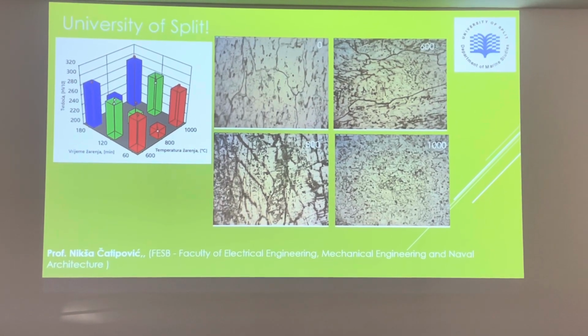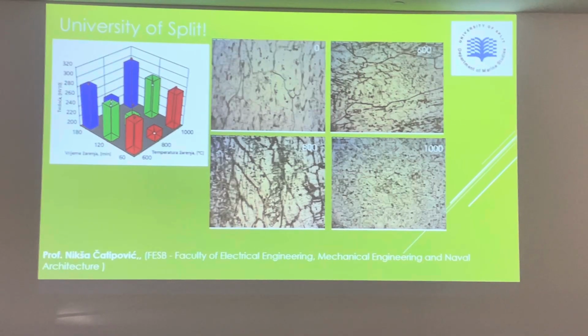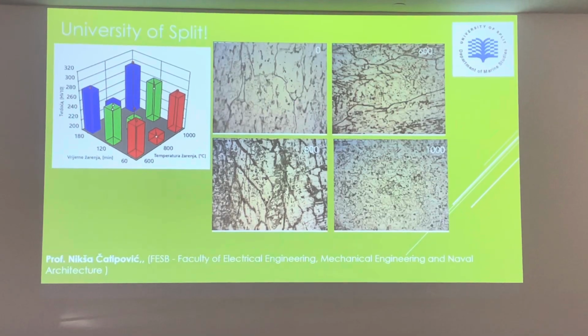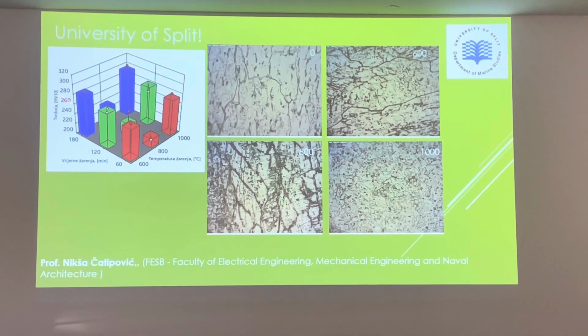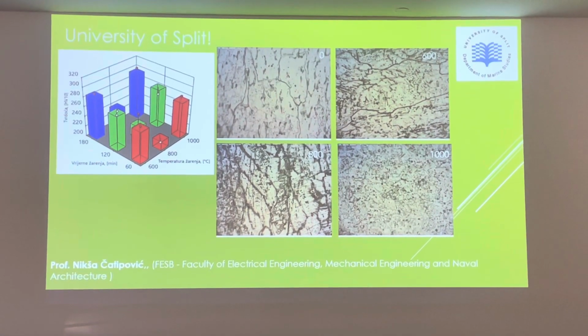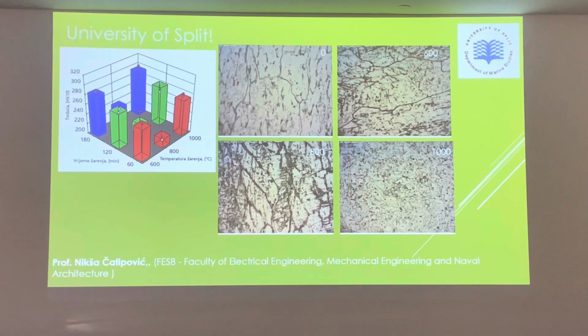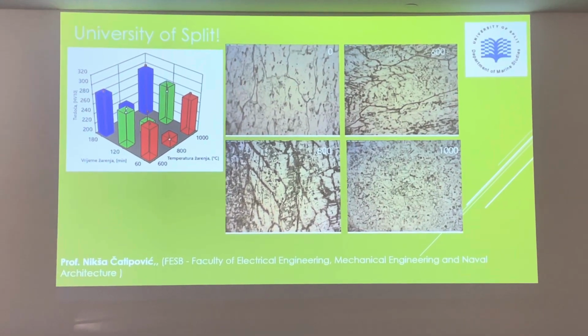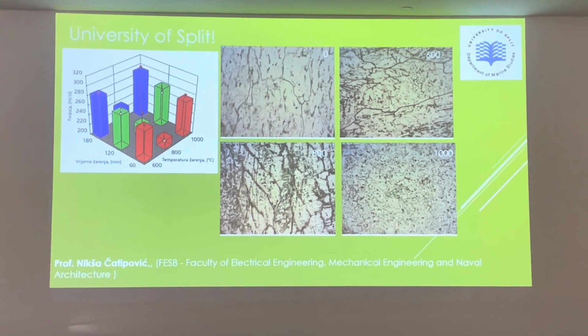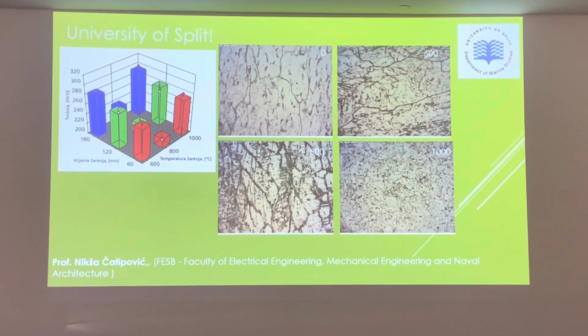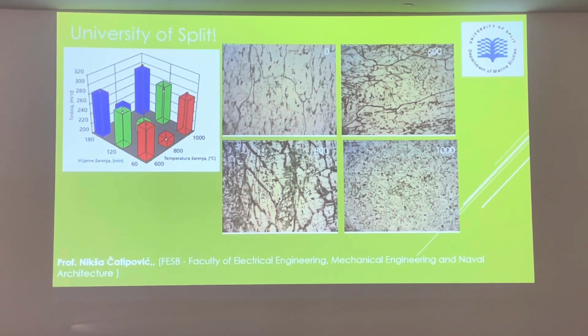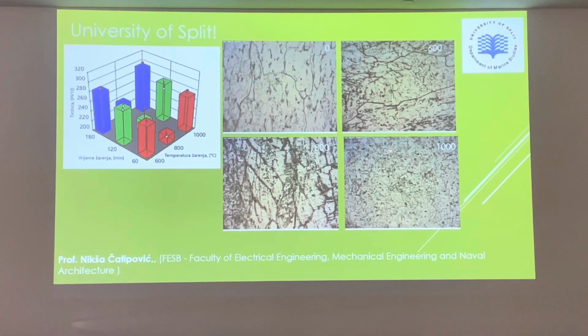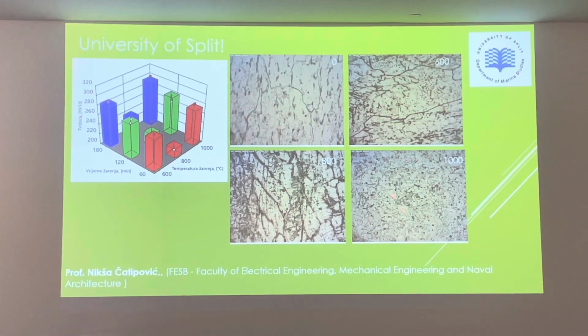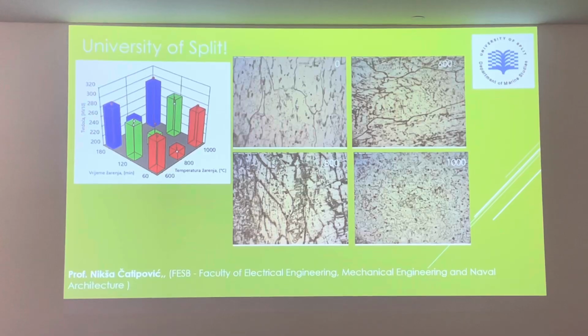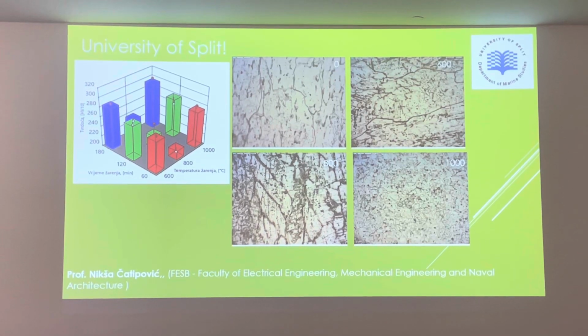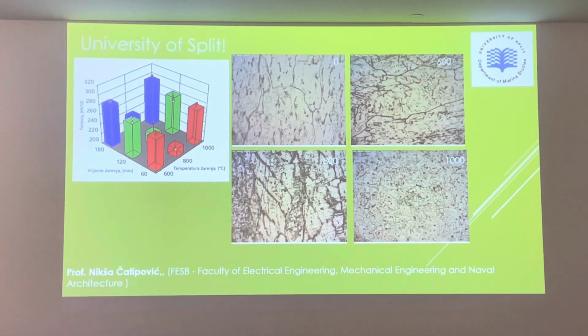We performed a study of different values of temperature and different times of heat treatment. And we found the dependency that at 600 degrees we have very stable properties. Next, at 800 degrees we have a decrease in mechanical properties, actually hardness is decreased. And after that at 1000 degrees we have again an increase in hardness. And what we have seen in microscopy investigation is that at 1000 degrees of temperature and 1 hour, we have fully recrystallized grains and a very fine grain microstructure, which in accordance with the Hall-Petch law leads to such an increase in mechanical properties.